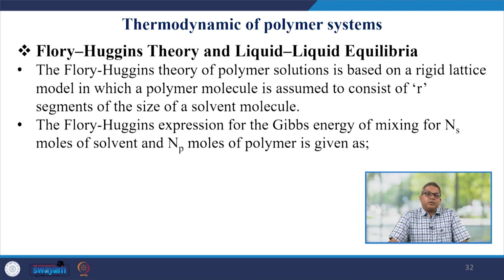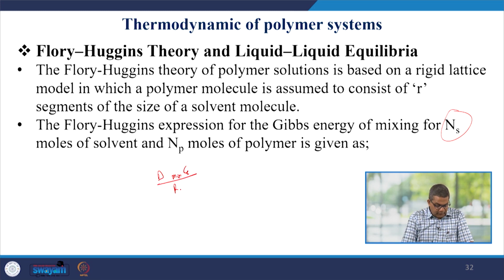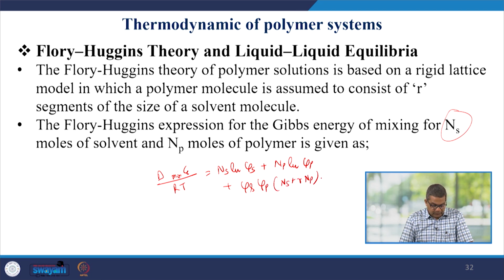Now, P.J. Flory, along with his co-workers, described this thermodynamic behavior in a more elaborate way, and they adopted the liquid-liquid equilibrium. So, as per the Flory-Huggins theory of polymer solution, which is based on a rigid lattice model in which a polymer molecule is assumed to consist of r segments of the size of a solvent molecule. So, the Flory-Huggins expression for the Gibbs energy of mixing of Ns moles of solvent and Np moles of polymer is given as delta G of mixing over RT is equal to Ns ln phi s plus Np ln phi p plus phi s phi p (Ns plus r Np) into chi.